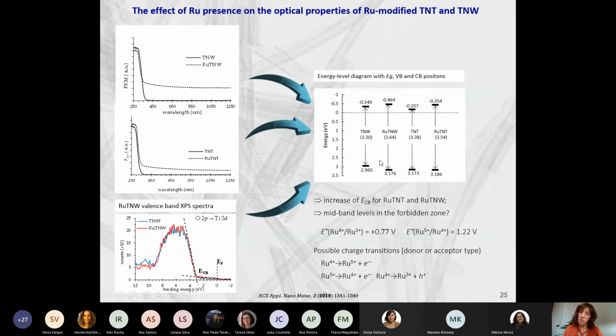Also important is, now that we know the exact position of these bands, we know that we can have some transitions here due to the presence of the ruthenium. We know the potential of the redox reactions of a ruthenium species that can be from donor or acceptor type, and are very important to play here in these forbidden zones.